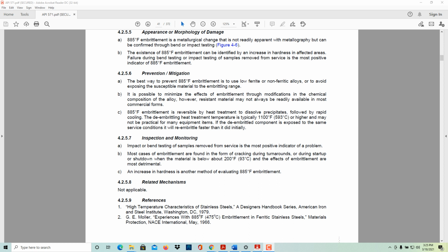Prevention and mitigation. The best way to prevent 885 embrittlement is to use low ferrite or non-ferrite alloys, or to avoid exposing susceptible material to the embrittlement range. It is possible to minimize the effects of embrittlement through modifications in the chemical composition of the alloys. However, resistant materials may not always be readily available in the most commercial forms. 885 embrittlement is reversible by heat treatment to dissolve precipitates, followed by rapid cooling. The de-embrittlement heat treatment temperature is typically 1100 F or higher, and may not be practical for many equipment items. If the de-embrittled component is exposed to the same service conditions, it will re-embrittle faster than it did initially.